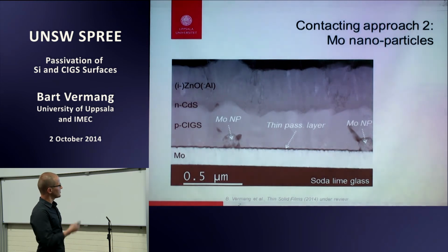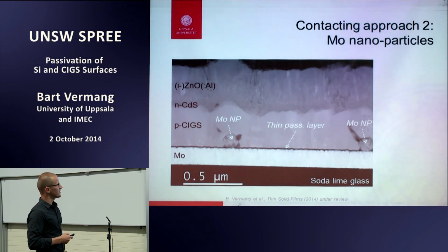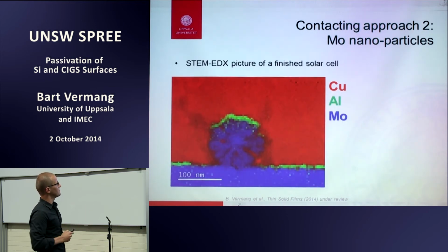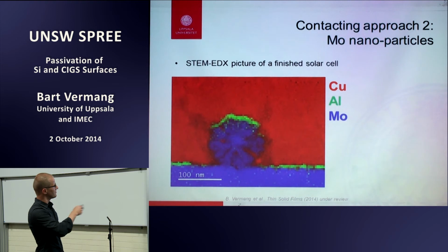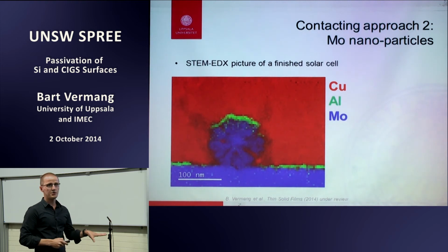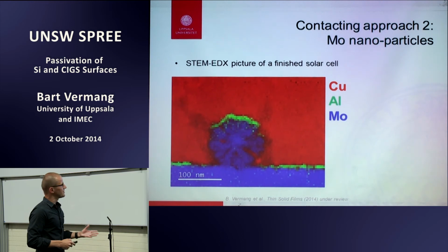That's what we did. So here you see a cross-section, you see the molybdenum nanoparticles, and it's very difficult to see the thin passivation layer in this SEM picture, but we also have STEM EDX pictures, and now you can see the passivation layer as well. So it's nicely covered on top and in between the nanoparticles. So there you're passivating. So you're using the molybdenum nanoparticles as point contacts.